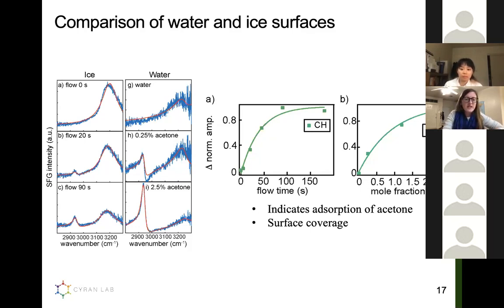As we increase the concentration or increase the flow time, we could see that the surface of ice in this case was at some point becoming saturated. So at some point we're layering the surface of ice with acetone, and then it gets saturated. After that, no more acetone is being adsorbed onto the surface, other than our monolayer of molecules that was there. And so this could also give us an indication of the adsorption coefficients for different molecules as well. In this case, we only looked at acetone for the moment, but it shows a unique way to get this information, adsorption isotherms as well.